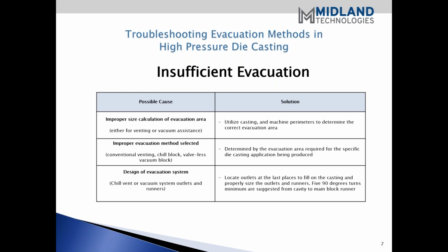Yep, they relate really. The first thing I do when I look at a casting is ask what does the customer require? What's the application of that casting? Is it thin wall and appearance a critical issue, or is it a casting that's going to be subject to and required to meet some strength requirements, or do we have to have a pressure tight casting? So each of those, and if you've been dealing with die castings for any period of time, you realize that each of these applications has a great effect on what you can get by with using: conventional venting, a chill block, or some type of the valveless vacuum blocks to evacuate the cavity. Right. So application is the big key factor here. And what do you select?